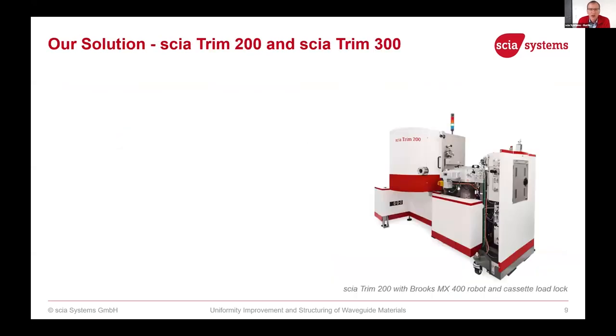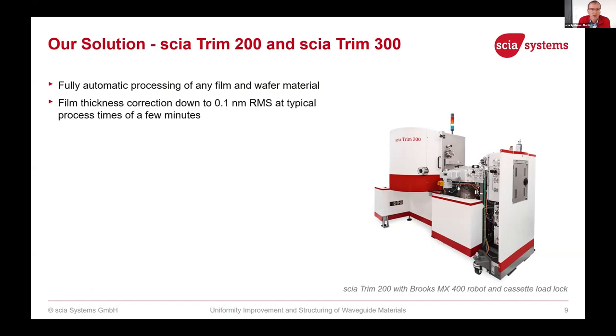And we have also achieved losses in the range of 0.14 dB per centimeter in some customer applications, but I cannot show any more detail on this. So here is a tool that is doing this process. It's a 200 millimeter tool, but can also be upgraded to a 300 millimeter tool with fully automatic processing of any film and wafer material.